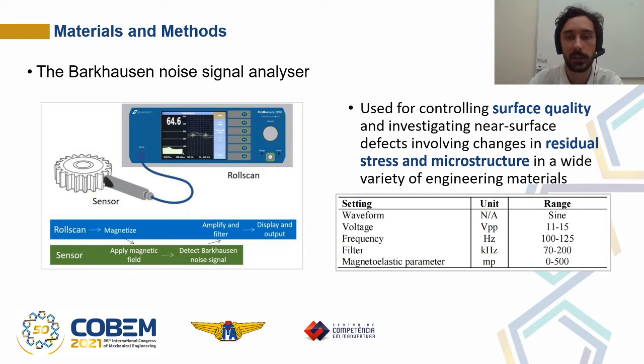The measurement process starts by inducing an alternating magnetic field, which tries to align the magnetic domains of the material in the direction of the field. This sudden change in the magnetization induces electric pulses, which are called Barkhausen jumps. These jumps are captured by the Rollscan, amplified, filtered, and displayed on the device screen. The equipment settings used for the Barkhausen noise measurements include the waveform, the voltage and the frequency of magnetization, and the filter of the signal, and the output is displayed in terms of the magnetoelastic parameter.